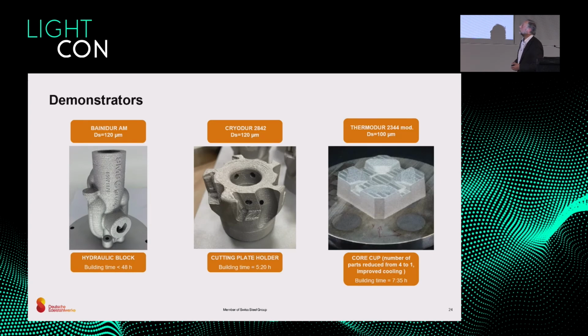So we'll show a few parts. The first one is a part of a hydraulic block. It's done with a layer size of 120 microns. Normally they use 30 to 40. It's very efficient, and you can do some kind of high-speed printing with this grade. That's a cutting plate from this grade, and we are just testing in the field a mold for plastic application.